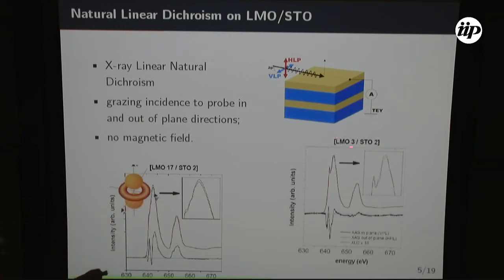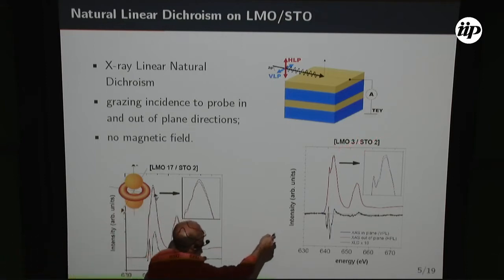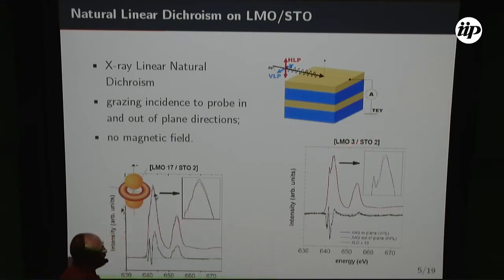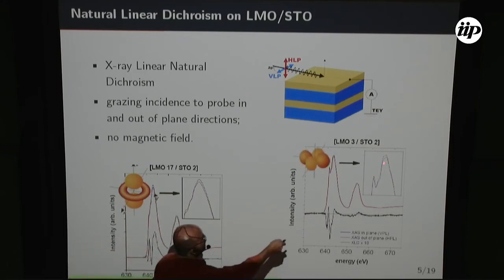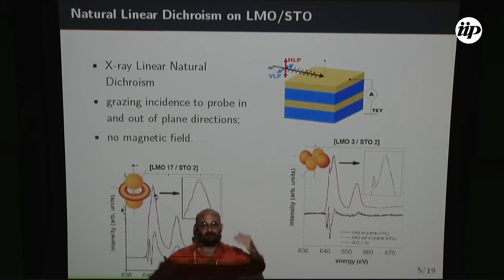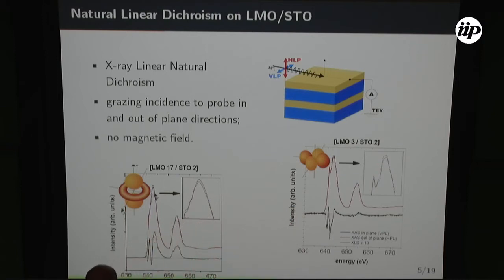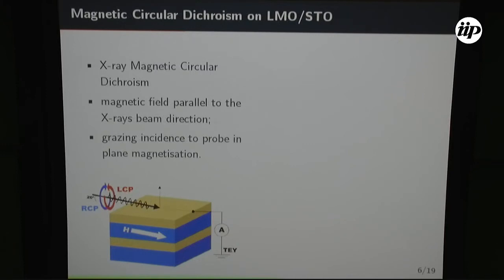Then there's the other sample with the thinner manganite layer. So 3 unit cells. In this case, it inverted here. So what it means is that there was an inversion on the population. Instead of populating more the Z² out of the plane, the electrons are populating more in the plane, X and Y, X² minus Y². So this is a change that we can correlate with the interaction, with modifications of the structure of the orbitals at the interface. Okay, that was one piece of information.